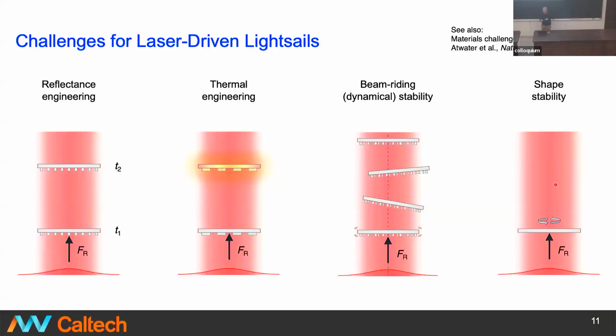So you might think of these as optomechanics issues for laser-driven light sails. One is making sure that the reflectance is high enough. The reflectance doesn't have to be within parts per billion of unity. Any reflectance between, say, 80 and 100% would be fine in terms of energy efficiency. The real issue has to do with absorption and thermal engineering.